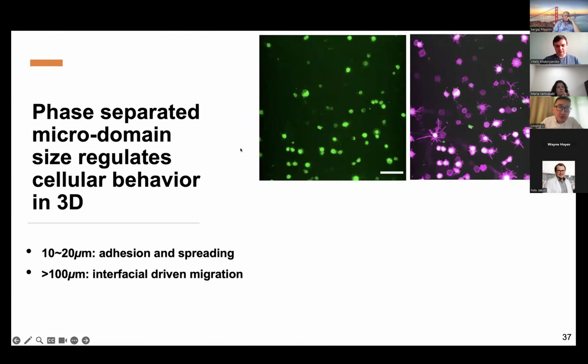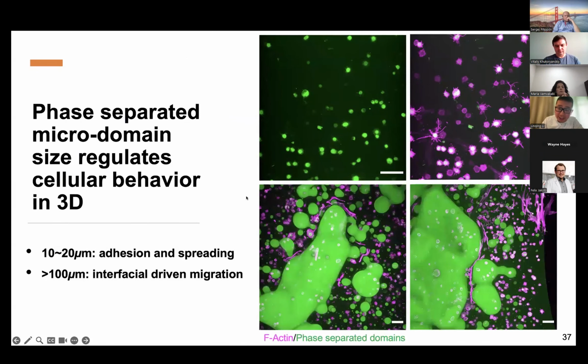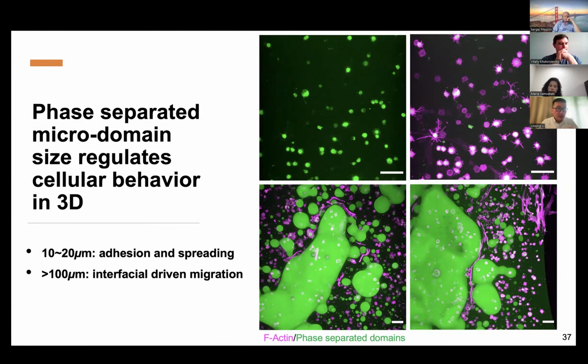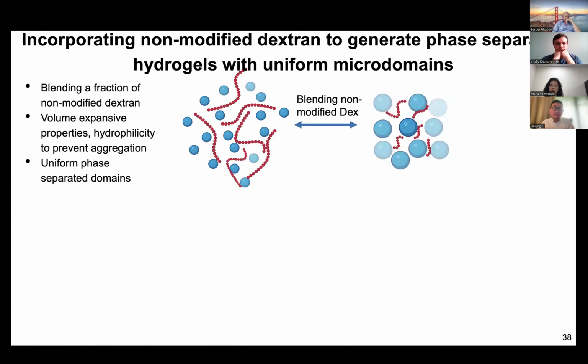We also went on to encapsulate the cells in 3D by changing the morphology. This is very early in our studies, showing that in the smaller size domains, the cells barely spread. They sort of internalize domains, which we don't fully understand, because we see overlapping with the green signal, which is autofluorescence of microdomains inside these cells. But with the larger domains, you can see the cells actually using the interface to migrate through the system. Again, we know the reviewers ask why you can't control this, and unfortunately, this is a phase separation condition. We really can't control the phase separation very well. So we are trying to tackle this problem by introducing a second component.